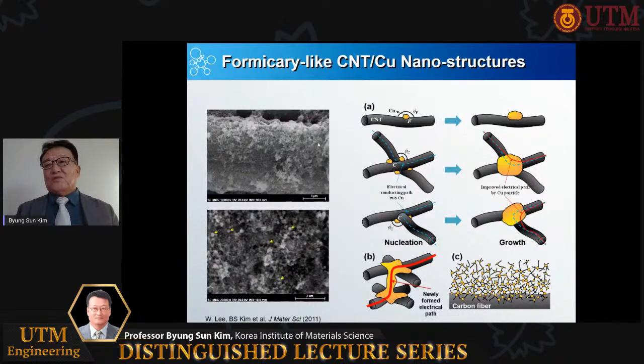Cathodic electrophoretic deposition process has been applied to produce unique carbon nanotube copper nanostructures on the carbon fiber surfaces. During the deposition process, ionized copper and positively charged CNTs are accelerated towards the carbon fiber under the applied electric fields. An interconnected formicary-like network of nanotubes and nanoparticles is formed, where the copper nucleation and growth occurs predominantly at the nanotube crossings and edge contact locations.